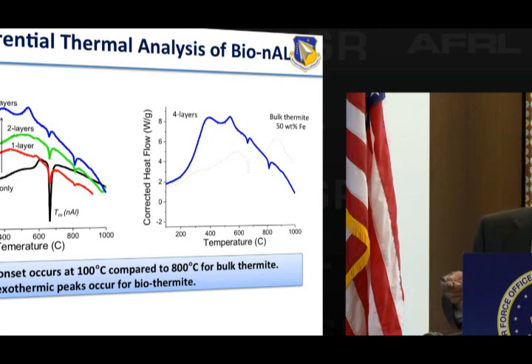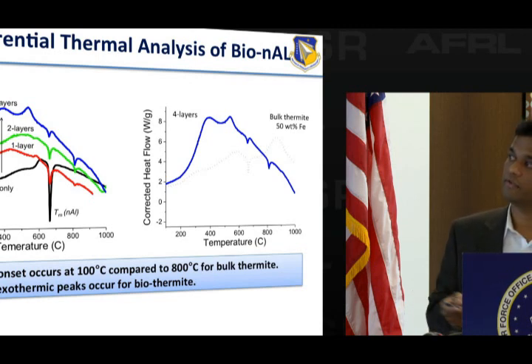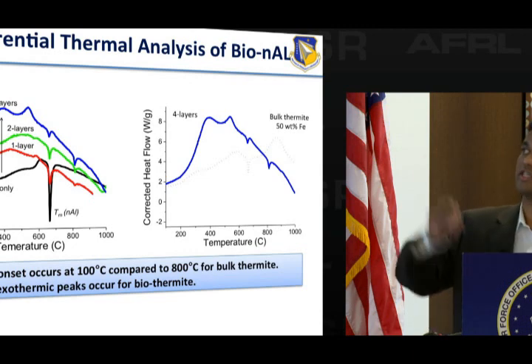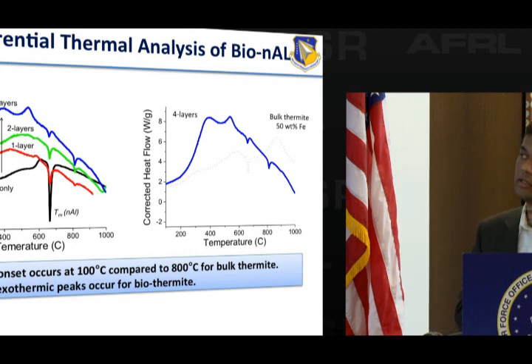and you can see by differential thermal analysis that the exothermic reactions start to creep up as you increase the layers. You can see new exothermic peaks that occur for some of these reactions. So you're actually seeing an increase in the combustion kinetics when you mix these things together.